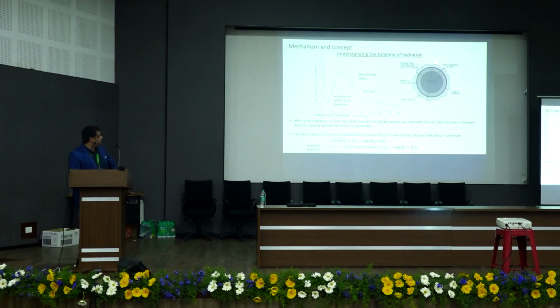And on the clinker grains, a layer of hydration compound is formed. And this has two types of product. One is called the outer product, and one is the inner product, which is much more densified than the outer product. And when you are talking about carbonation, CO2 basically reacts with this outer product and deposits the calcium carbonate on the clinker grains and in the surrounding of the clinker grains, right?